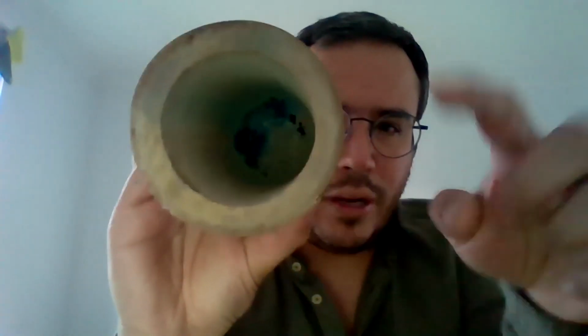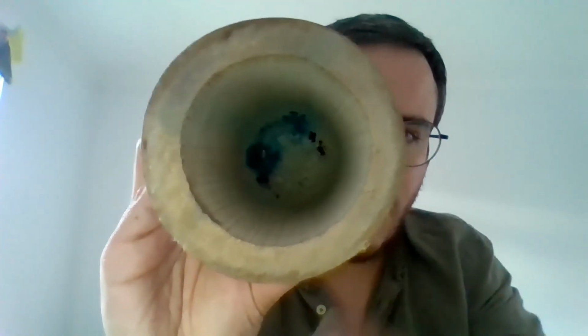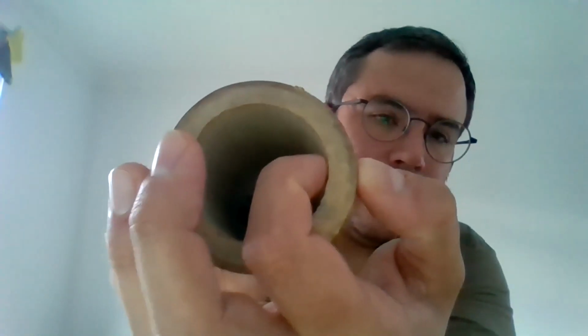Laminated bamboo, it will definitely depend on the type of bamboo or the bamboo species that you are using. Because of the very thin cross section, I actually have a piece of bamboo here. So remember that you are trying to have rectangular cross sections out of circular cross sections. So bamboos that we use for laminated bamboo are normally called woody bamboos, and they have a diameter of around 120 to 160 mm, and the thickness of the wall is around 10 to 15 mm.